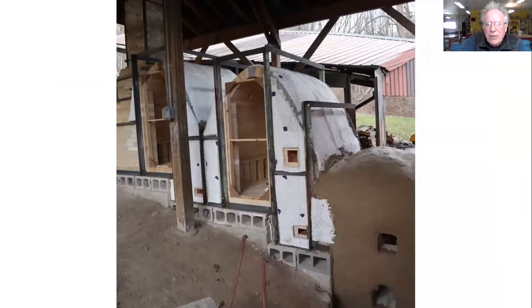And then we start to put the castable covering on it. And the castable holds the kiln in place. It gives it a little more rigidity, gives it a little more oomph. It insulates, helps seal off the outside air from the kiln with wood firing. It's a passive process. It's not under pressure like it would be if it were a gas kiln with pressurized burners. A wood kiln draws its air source from wherever it can get it. So if you have a lot of leaks in a kiln, it's drawing air into it, and that might not be conducive to getting the kinds of color or reduction in the glazes and the clay body that you want.